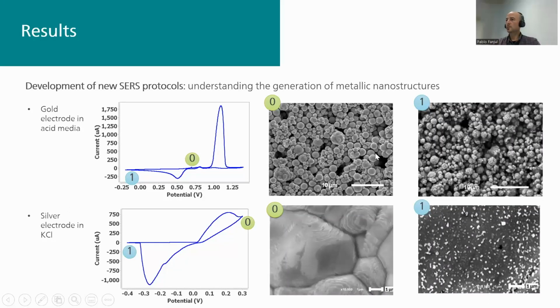And what we can see in the different pictures of the scanning electron microscope is that we can generate some increased roughness in the surface of the gold particles that we have in the electrode. So we increase the surface area by increasing the roughness with these nanostructures or with these different shapes that we have in our gold microparticles, and that will be the surface that is SERS active. However, in this case, if the surface is not pretreated, we will not have the SERS effect.